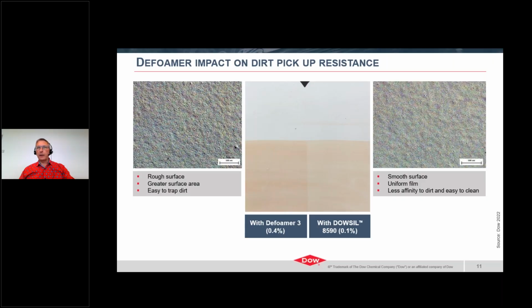And just finally, still for the same featured material, in this case, looking at the comparison with the mineral oil-based defoamer, we can see the results of the pickup resistance in a slightly different paint. In this case, it's a 46% pigment volume concentration and 36% volume solid, again, based on acrylic binder. We can see a clear difference in the dirt pickup resistance between the 2 samples.